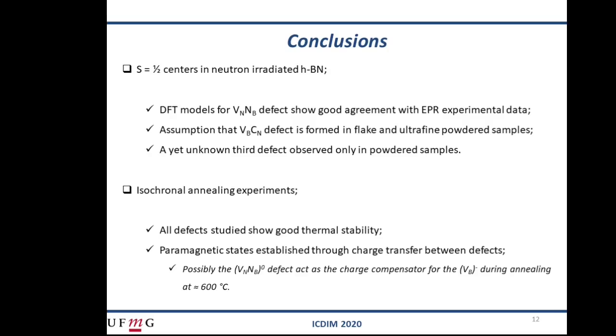Finally, what we can present as general conclusions so far. 1. The neutron radiation produced 4 point defects in HBN: the negative boron vacancy with spin 1, with 3 more spin 1/2 defects, which are the VNNB defect, whose DFT models are in good agreement with the EPR experimental data. 2. The VBCN defect observed only in flake and ultrafine powdered samples. And 3. A third unknown defect, but based on thermal annealing experiments, plays an important role in the thermostability of the spin 1/2 defects in neutron-irradiated HBN.